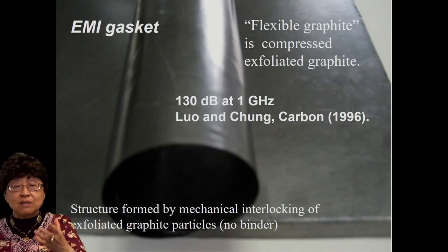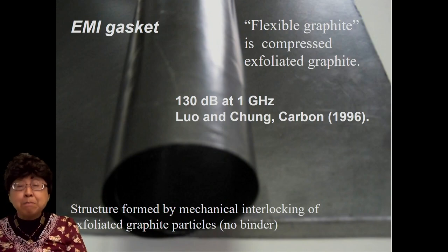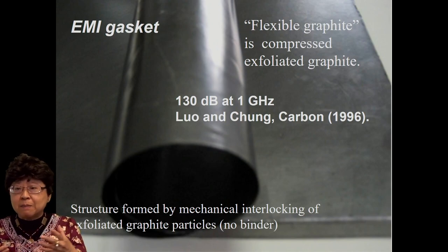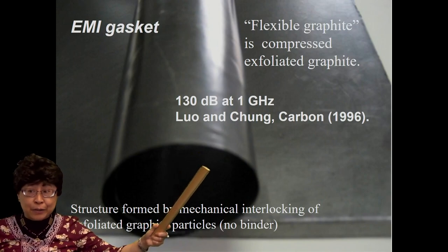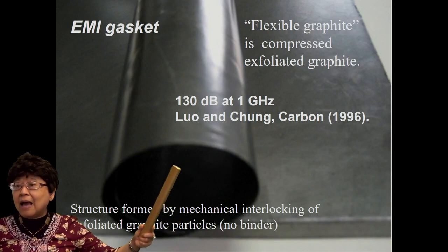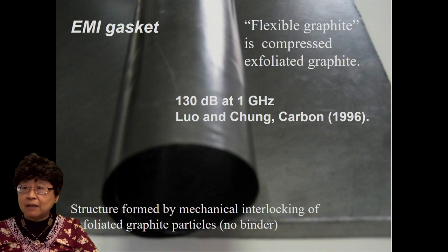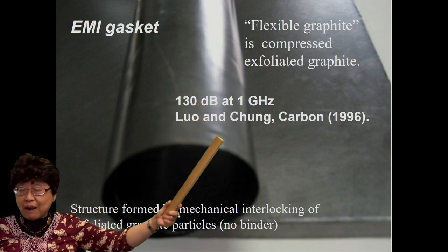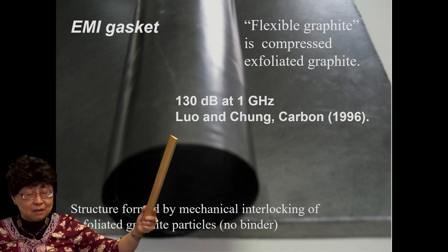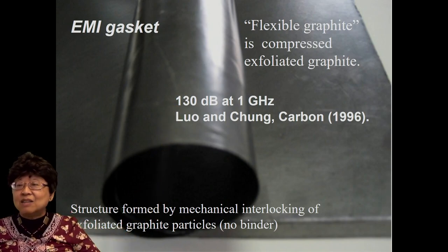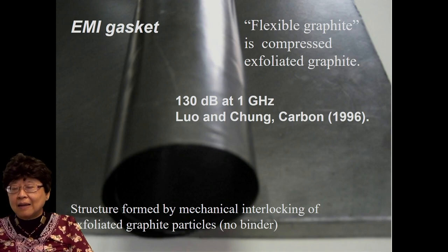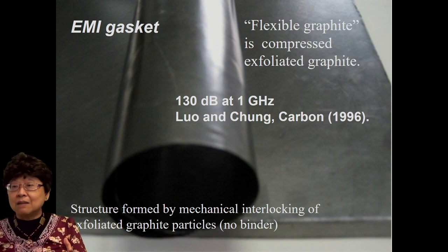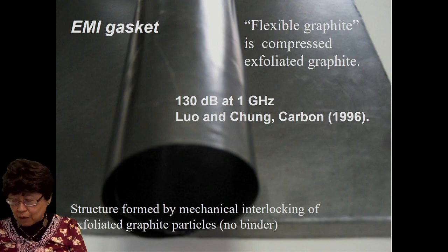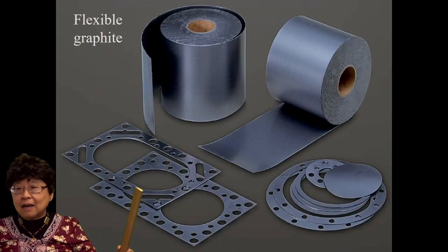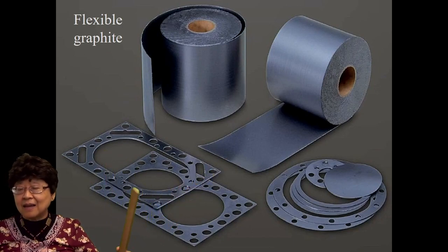And if you take a lot of these exfoliated graphite pieces and compact them, because of the cellular structure, there is mechanical interlocking between these pieces, and so it becomes a sheet in the absence of any binder. Okay, and this sheet is actually flexible, and it is a little springy in the direction perpendicular to the plane of the sheet. And this is called flexible graphite. And I discovered that this material is excellent as a shielding material with this record high shielding effectiveness of 130 dB. And that is because it's not only conductive, it also has substantial surface area per unit volume. And one can cut the sheet to make gaskets, okay, EMI gaskets.